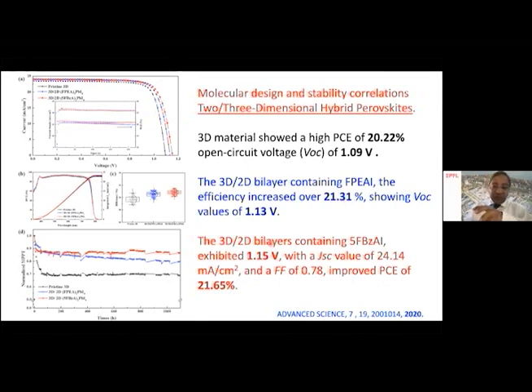And similarly, if you take the pentafluorophenylethylammonium cation deposited on top of three-dimensional perovskite, it increases the VOC from 1.09 to 1.15, and the power conversion efficiency went up from 20.22 to 21.65. Similarly, you can see the stability enhancement. Compared to our reference sample, pure 3D perovskite, after 1000 hours over 30% efficiency is lost. But with the pentafluoro and fluoro amine, they are much superior to the reference sample. So this way you can improve the stability of the perovskite solar cell using this interlayer engineering.